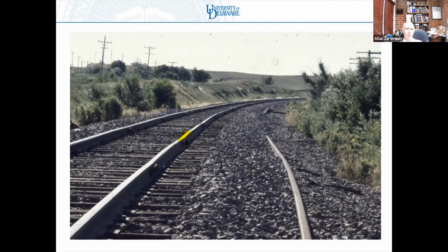The batter is so severe that not only does it crush the rail, it actually degrades the ballast and sleeper underneath it. And this is one of the reasons why nobody puts concrete sleepers under joints. If you have to have a joint in concrete sleeper track, you need to put wood sleepers there because the dynamic forces are so high, they will actually crack your sleepers, going back to our whole discussion of sleeper cracking. And international practice throughout the world is if you have high dynamic impact forces, such as the joints, you can't live with your concrete sleepers.